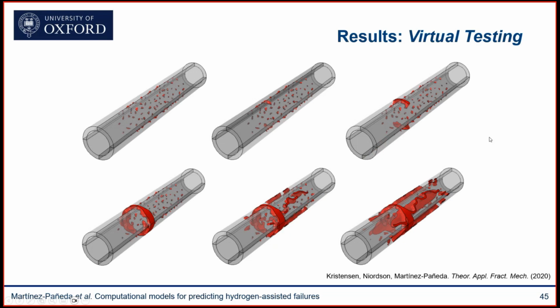You can see it here as well. But I mean, the key takeaway here is that we finally have a tool that allows us to predict when hydrogen-assisted failures will happen as a function of environment, the material, and the loading conditions. And as you can see here, this tool is not only able to deliver predictions at the lab scale, but it's also able to do so at the scales and complexity conditions relevant to engineering practice. No matter what complex the problem is, we can handle it.